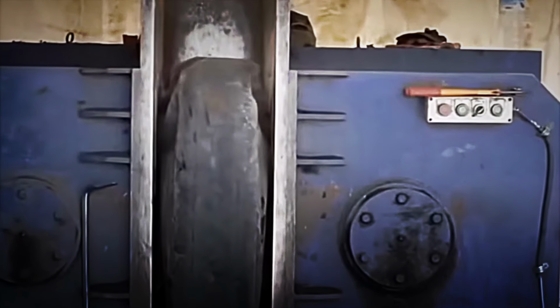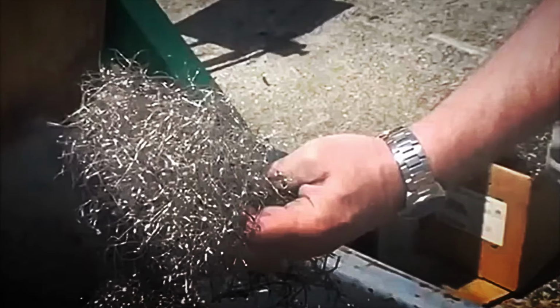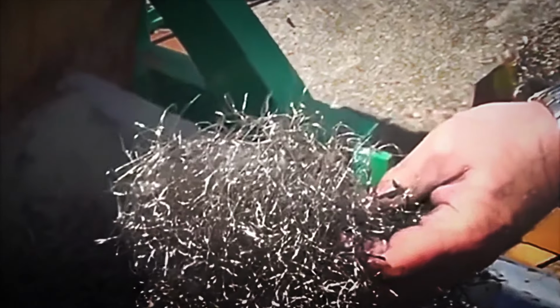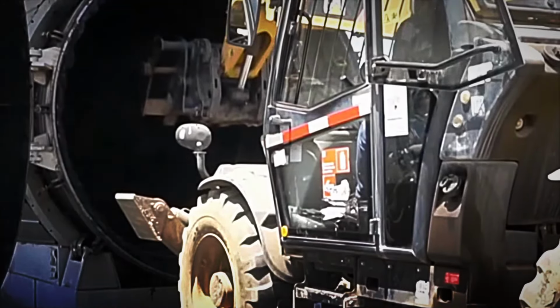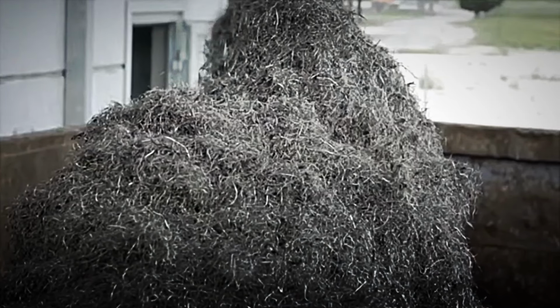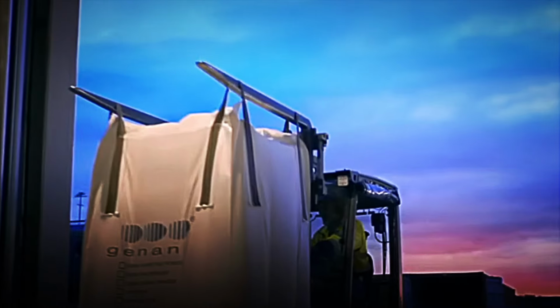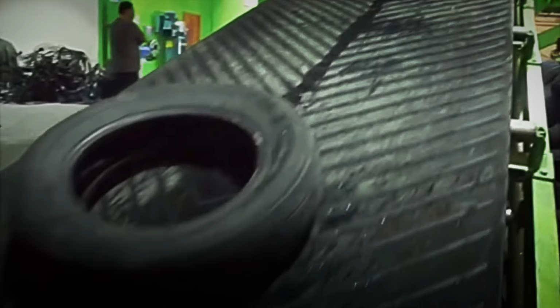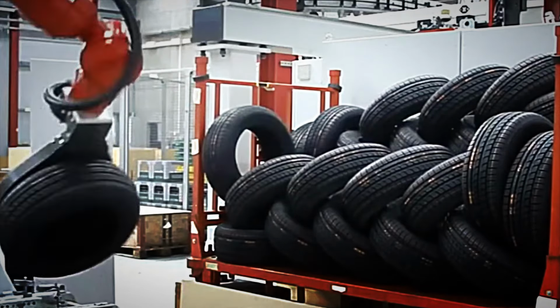At this initial stage, the tires are introduced into specialized machines for ring extraction. Inside, a hydraulic system with high-strength hooks digs deeply into the tire's bead and applies immense force to tear the steel core apart in a matter of seconds. The tension is so extreme that the rubber body twists and deforms violently during the process. On average, each heavy-duty truck tire can yield around 2 kilograms of high-quality carbon steel.